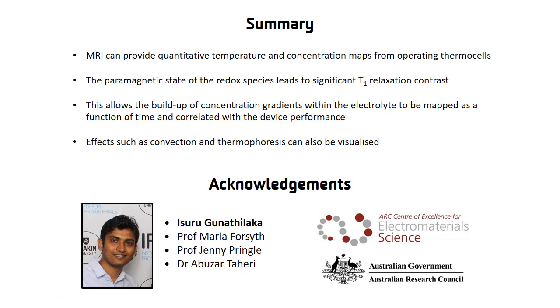So just to summarize, I've shown that we can use in situ MRI experiments to obtain quantitative temperature maps and concentration maps from operating thermocells. The paramagnetic state of the redox species leads to significant T1 relaxation contrast, and this is a big advantage for using MRI to study these particular types of devices.